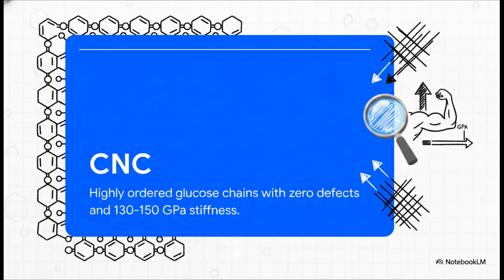Let's zoom in even further to the micro level to see how this actually works. We're talking about cellulose nanocrystals, or CNCs. Picture these as highly ordered, densely packed chains of glucose with almost zero structural defects. Because of the super high density of hydrogen bonds inside this crystalline structure, CNCs can hit a tensile strength of up to 7.5 gigapascals. That completely rivals industrial carbon fiber. And they boast a Young's modulus, which is basically how we measure stiffness, of 130 to 150 gigapascals. Nature has basically engineered a flawless structural component right down at the atomic level.